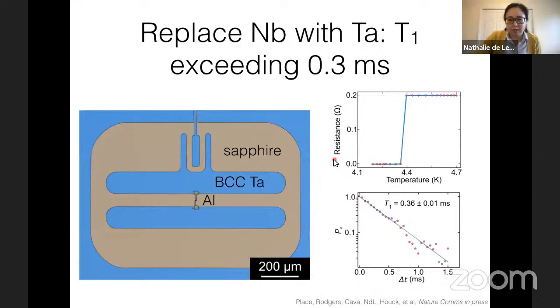Okay, so the headline result after all of those improvements is that we're now able to make planar transmons with lifetimes exceeding 300 microseconds, which is a factor of 3 or so improvement over the prior state of the art across many gigantic efforts. So this is all that you need to know. You don't need to listen to the rest of it, but basically we're now able to get these really long T1s.